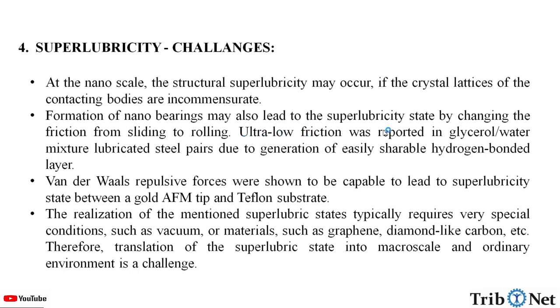Ultra-low friction was reported in glycerol-water mixture lubricated steel pairs due to the generation of an easily shearable hydrogen-bonded layer. Van der Waals repulsive forces were shown to be capable of leading to a superlubricity state between a gold AFM tip and a Teflon substrate.